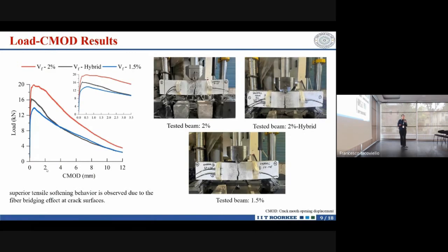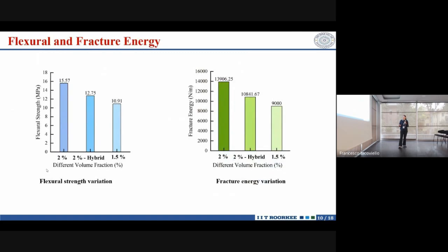So these are the results that we have got from the load CMOD. As you can see, the fiber percentage variation is affecting the post-cracking profile significantly, which infers that fiber volume has a greater influence on this. And the flexural and fracture energy is also higher for 2%. The main reason is that, for crack resistance, we have more fibers engaged in the crack bridging action for the 2%.